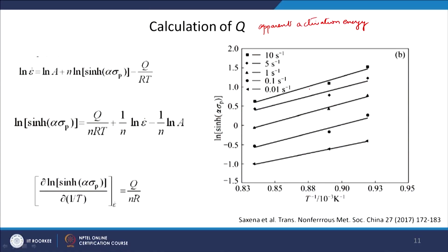Also if you remember, we were seeing some flow stress curves where at low temperature it shows strain hardening, then at some intermediate temperature it shows dynamic recovery, and at even higher temperature it shows dynamic recrystallization. So, steady state, sometimes softening and so on. The idea is that the microstructure is continuously changing, it is dynamic. So, when we calculate the activation energy from the data of different temperatures, the activation energy you are getting is going to be an apparent activation energy.